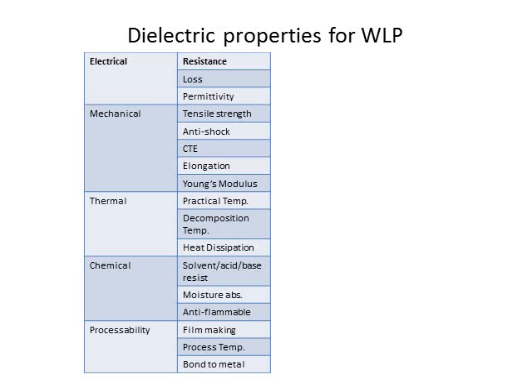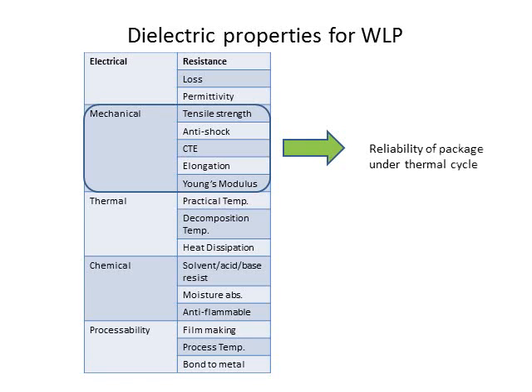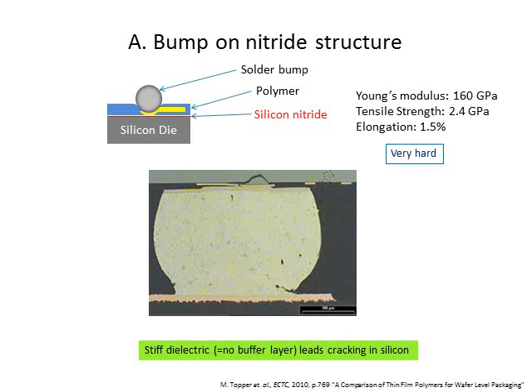This table summarizes the properties required for the dielectric in wafer level packaging. There are so many properties that need to be satisfied. In this talk, we will focus on the mechanical properties because they are connected to the reliability of the package under thermal cycling test. This is the so-called bump-on nitride structure. In between the silicon die and the conductive layer, such as copper and solder bump, we need to have an insulation layer. And in this case, silicon nitride is used as an insulation dielectric.